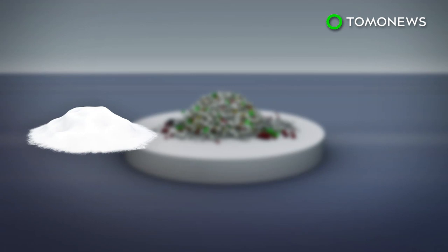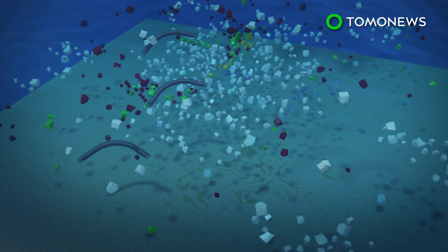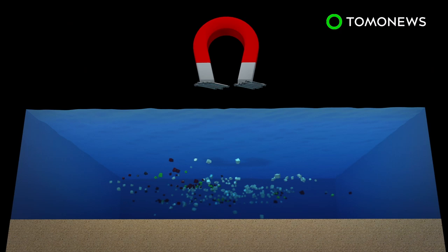The result is that the microplastics are converted into salt compounds, carbon dioxide, and water. During a trial, researchers found that the spiral nanotubes were able to reduce the volume of microplastics present in polluted water between 30 to 50 percent in the span of eight hours.